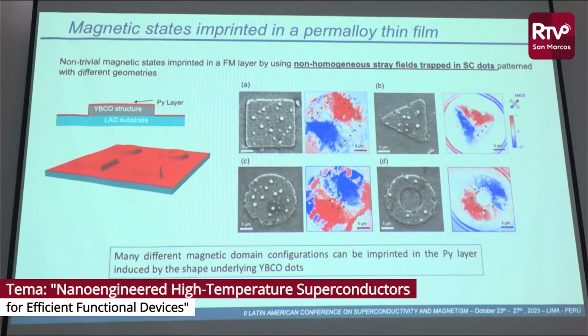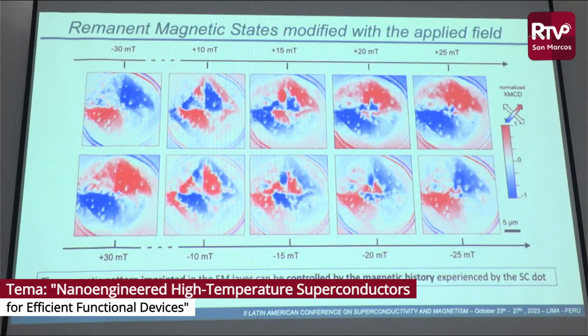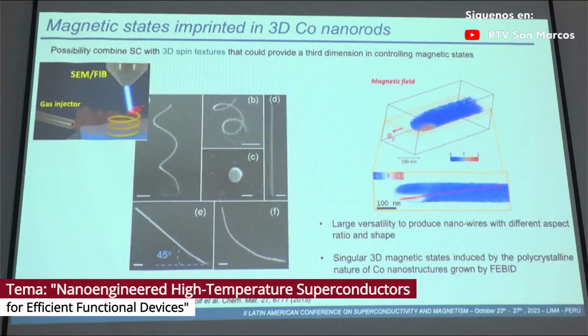And in these systems, for example, here I show a square dot and the evolution of the remnant magnetic field that is imprinted in the ferromagnet by using the magnetic field trapped inside the dots. And what we see is that many different non-trivial structures could be imprinted and could be stabilized at zero applied field just by using the trapped magnetic field in the superconductor. And these different structures could be used in order to build different memory levels.